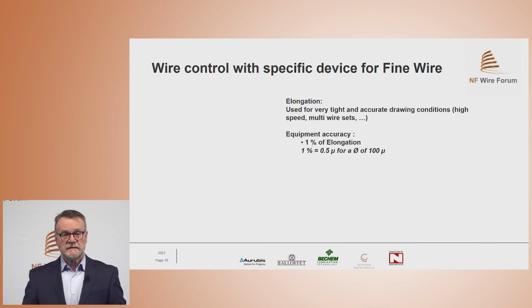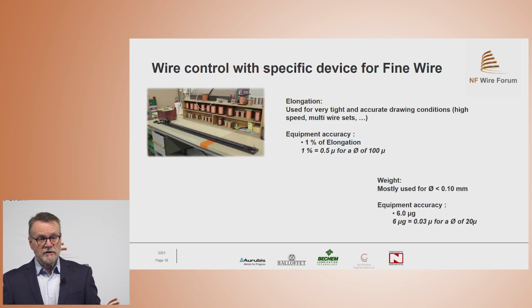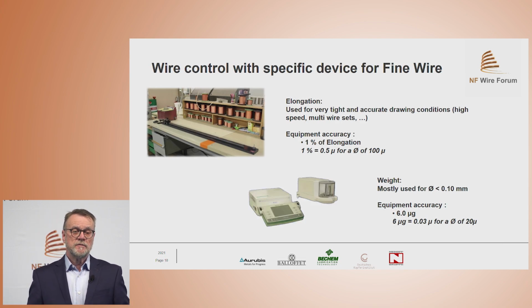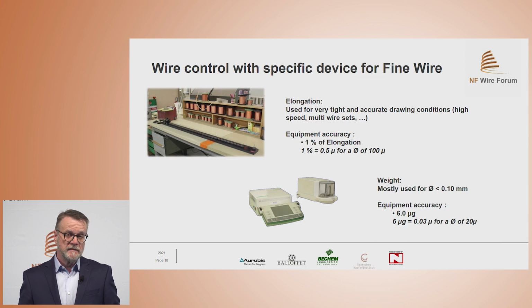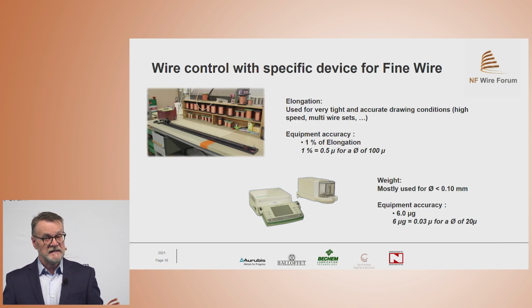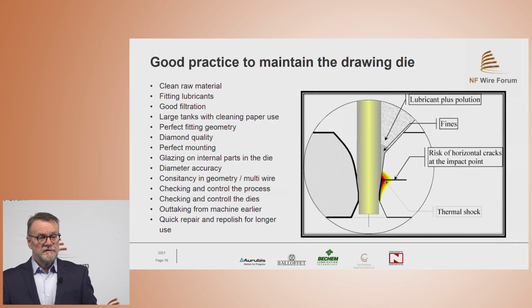The important point is the wire control. For wire control, we can use an elongation check for tight and accurate drawing. This means 1% elongation checking is 0.5 micron for a wire with 100 micron. If we are smaller than 100 micron, we can also use the weight. The accuracy is about 6 microgram. This means 0.03 micron for a wire with 20 micron. It's very, very small.